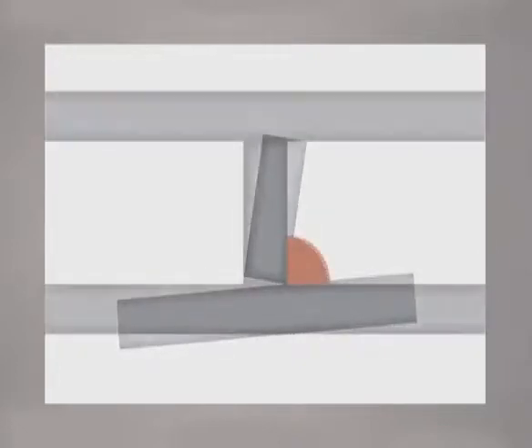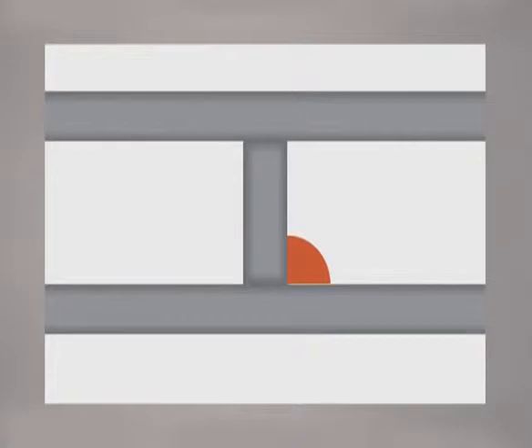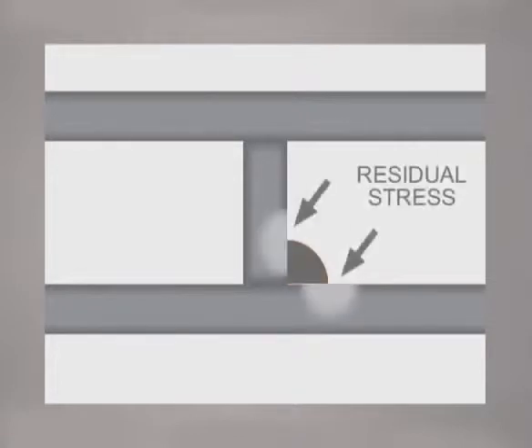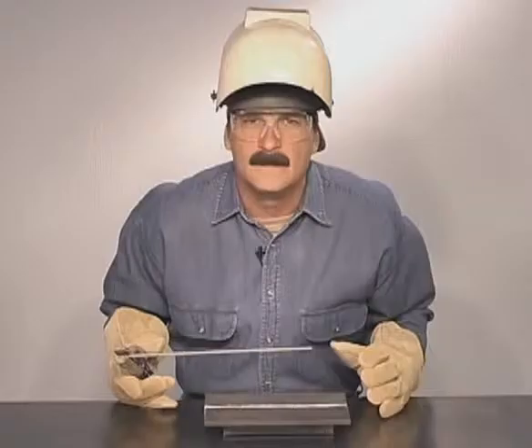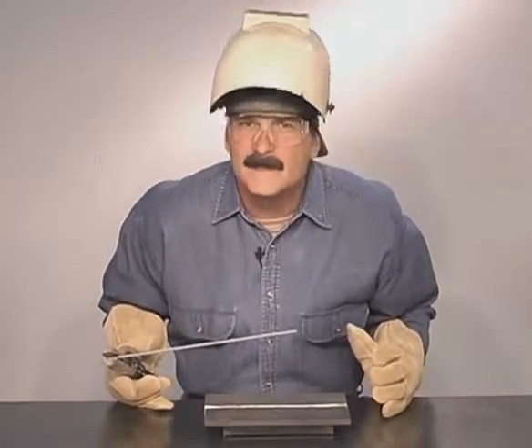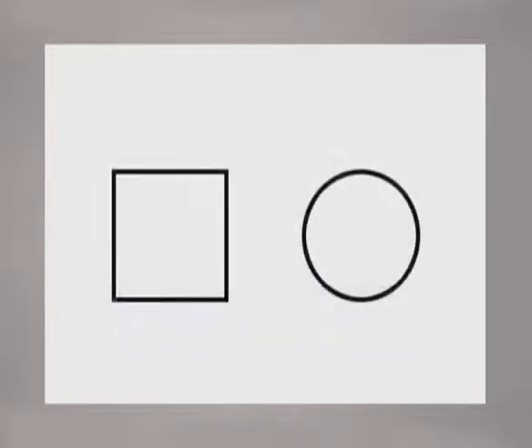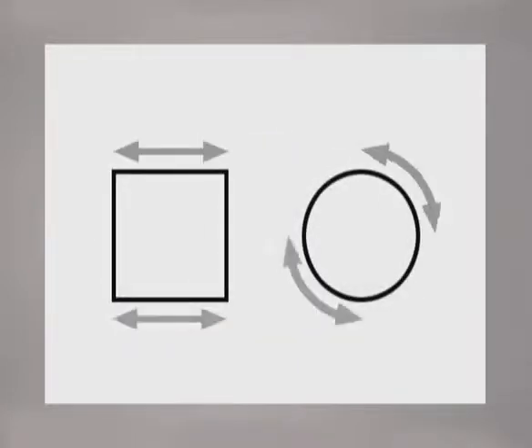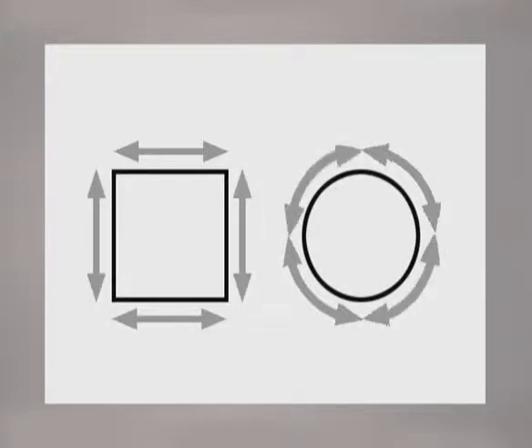If the pieces being welded are trapped, the molten weld metal still contracts, leaving some residual stress in the metal. There isn't any way to stop this. The metal is going to move. Whenever possible, weld on both sides to reduce the draw, and on pipe or square tubing, use a sequence of welds to help control the draw.